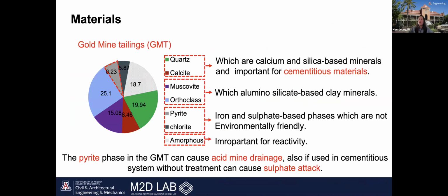So in this study, we used gold mine tailings, or GMT. The analysis of GMT shows that it contains several crystalline phases, including quartz and calcite, which are important for cementitious binders. It also includes clay minerals such as orthoclase and muscovite, which are mainly silica and aluminosilicate-based materials. In addition to these, GMT also contains pyrite and sulfate-bearing phases. These are problematic because pyrite can oxidize and produce acid mine drainage, which is harmful to the environment. And if it is not treated properly, it can also cause sulfate attack when used in cement-based materials.